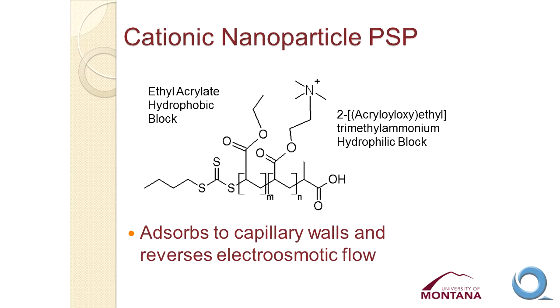So we've synthesized these cationic nanoparticles. They do, in fact, adsorb to the capillary walls. Everything looked like it was working very nicely until we tried to do some separations, and you see very poor peak shapes, very long retention times for compounds just because they're interacting with the nanoparticles that are adsorbed to the capillary walls. So we can't just use the nanoparticles to adsorb to the walls and reverse the electroosmotic flow. We need to find some other way to do that, because if we do this, we end up with very poor separation efficiency.